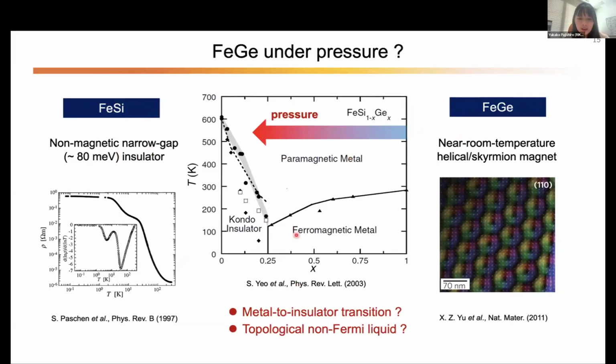So actually in the chemically doped system, this kind of phase diagram is constructed, and indeed they observe a first-order phase transition from the ferromagnetic metal to the non-magnetic insulating state. But because of the impurity of the single crystals, or the very small size of the single crystals they obtained, a very detailed transport measurement has not been done in this system. So we decided to apply pressure all the way from iron germanium to tune the system to iron silicide and explore if we can obtain a metal to insulator transition, as well as a possible topological non-Fermi liquid state as reported in manganese silicide.